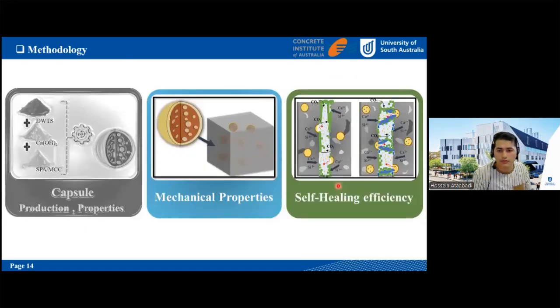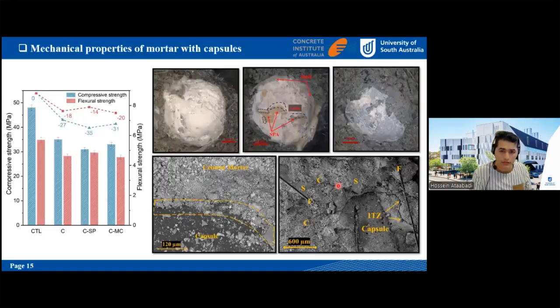Okay, so after production of the capsule, it's going to be used in the cement mortar samples. So we added the capsule in different ratios. Here I'm just presenting one of the ratios we have. Here we added 4% of the capsule, replacing the sand in the mortar samples. So here we see that the compression and flexure strengths both reduce by around 20%. The compression actually reduced around 30%, and the flexure reduced around 18 to 20%.